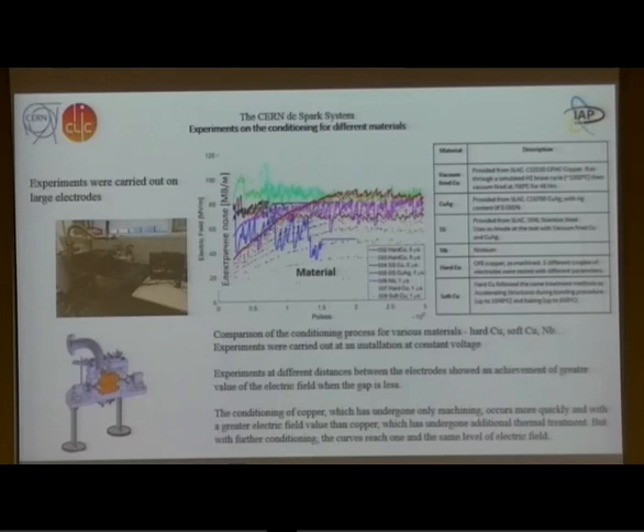This slide shows a comparison of the conditioning process for various materials: hard copper, soft copper, niobium, et al. Experiments were carried out on the installation at constant voltage. The conditioning of copper that has undergone only machining occurs more quickly and at a greater electric field value than copper that has undergone additional thermal treatment.